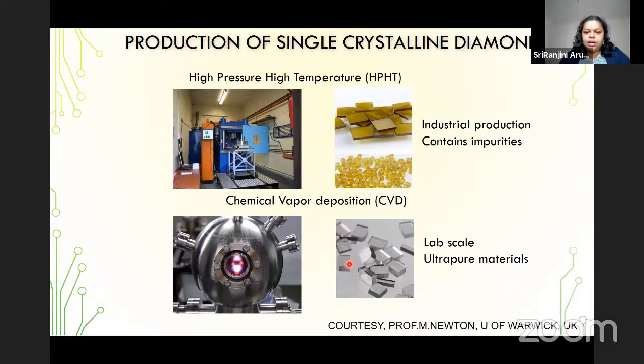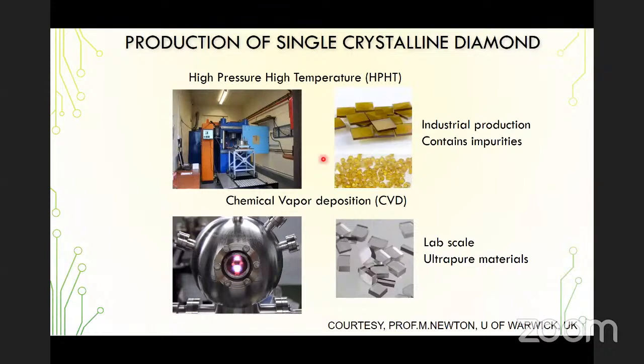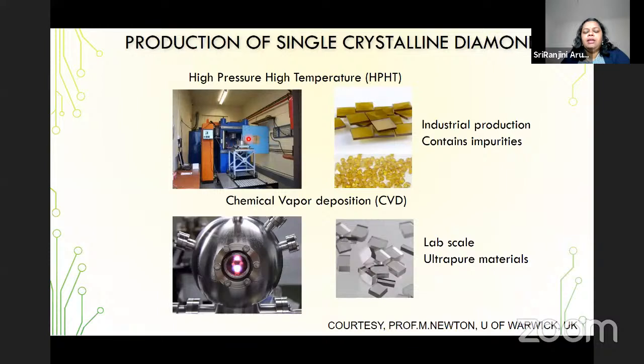We can also use a naturally occurring mined diamond, which is more expensive. So we make it at laboratory scale or industrial scale, where we do the production of single crystalline diamond. It is a high pressure, high temperature method by which industrial production is done. You can see this is one typical setup. The diamond we get here is a little impure because of the industrial scale production method. But if you do it by chemical vapor deposition at laboratory scale, we can get a very ultra pure material, which is ultra pure diamond substrates.